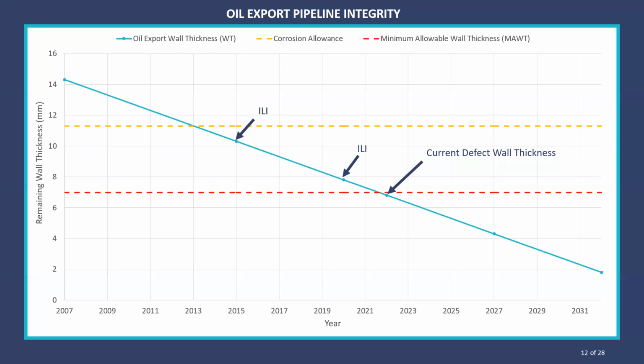But the main thing we're noting right now is that it's probably very unlikely this pipeline will be able to operate all the way to 2032 based on its wall thickness. So our immediate mitigations would be implementing a monthly pigging regime to shore, reducing the water content from 2% right now to ideally 0.5%, but 1% may be more manageable, and also introducing biocide into the oil export system.